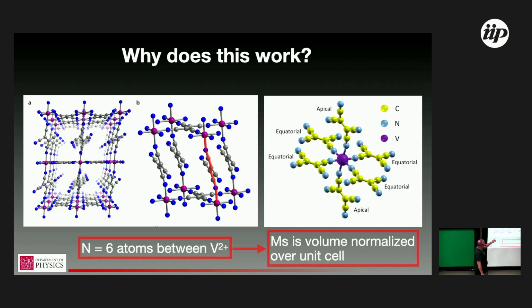But what that means is that we have very strong exchange coupling where there is material, right? So that's a large energy scale for the spin alignment in this direction, but the overall spin volume is quite small. Coming back to Michael's question about the saturation magnetization, typically we get 50 to 100 Gauss saturation for VTCNE, which is, I'm blanking on the number, but at least a factor of 10 smaller than YIG, which is already considered to be a relatively small MS in the community of magnets. So I think this is, if not quite a complete model, a smoking gun pointing at why we can have these very nice magnon properties in the system: the molecular nature allows us to find this regime where exchange is strong and MS is small.